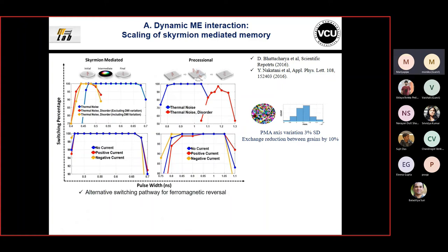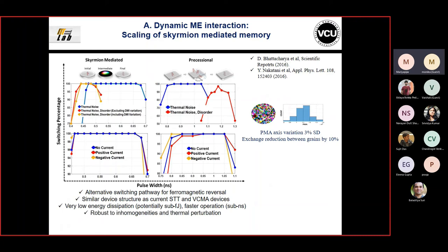Having looked at fundamental aspects of nanoscale magnetism and controlling them in two cases - a nanomagnet and a skyrmion - let's see the practical importance. For the skyrmion: there are a lot of racetrack skyrmion devices, but our interest is skyrmions in patterned structures where you don't have a background magnetic field from the rest of the material. What you can do is have a ferromagnetic state, reduce the anisotropy, the spins in the center curl the peripheral spins out, forming a skyrmion. When you increase the anisotropy again, the peripheral spins move inwards, pushing the core and making the magnetization point downward - getting a ferromagnetic reversal from up to down through a specific skyrmion pathway.